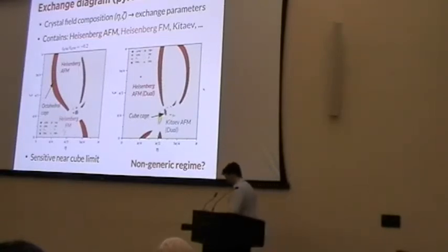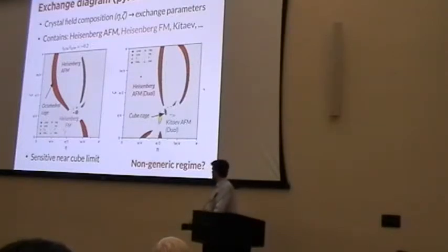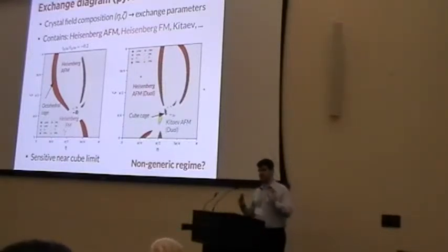So more broadly, you can look at how this depends on things like crystal field parameters. What I'm showing here is some parameterization of this ground doublet, which again varies from material to material. So perfect octahedron, say here, and then this would be a perfect cube, and then in here is some kind of trigonal distortion. What I've drawn here is basically what the dominant exchange is. If you see gray, it means that nothing's dominant. And when you see a bright color, it means one of the exchanges is dominant.